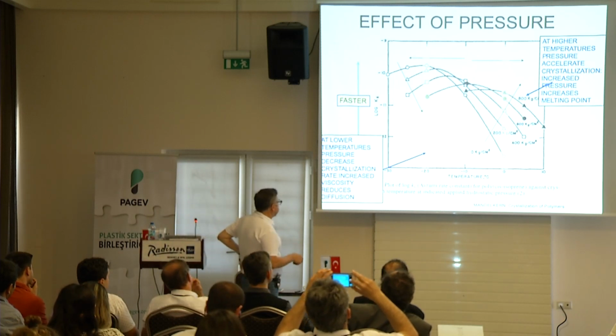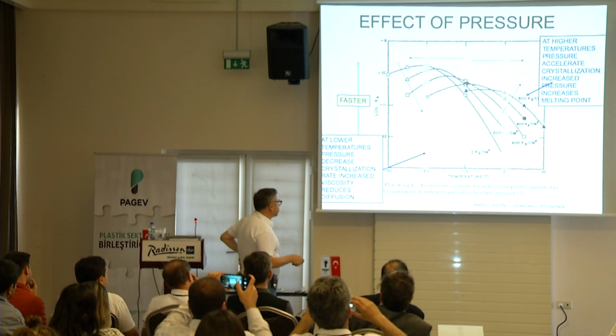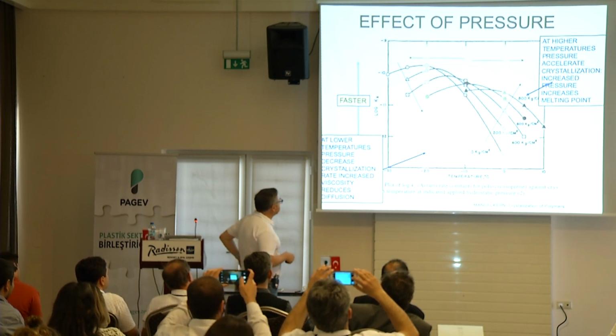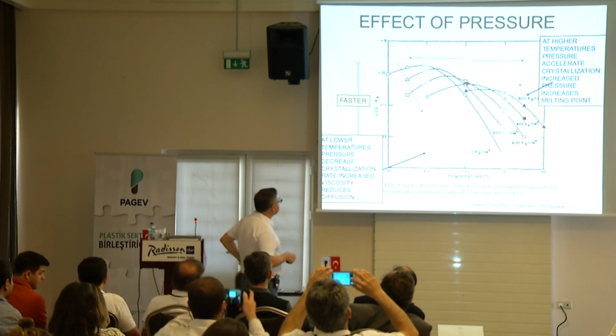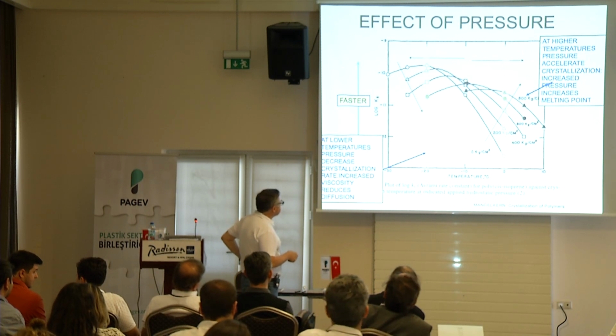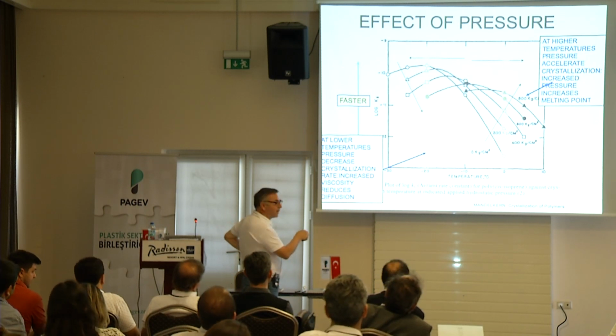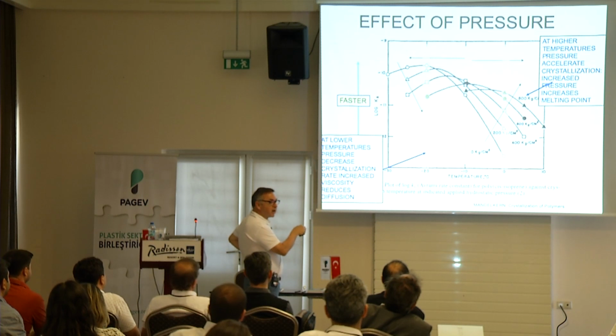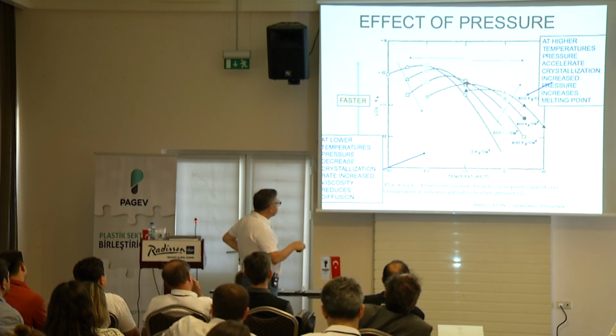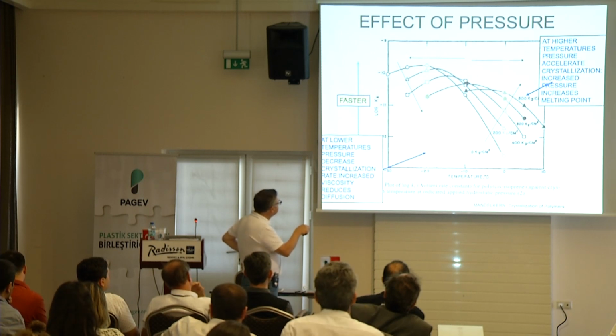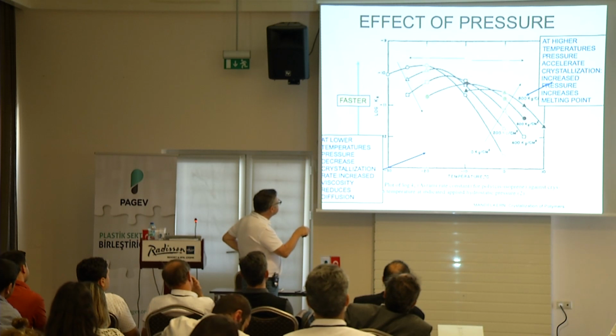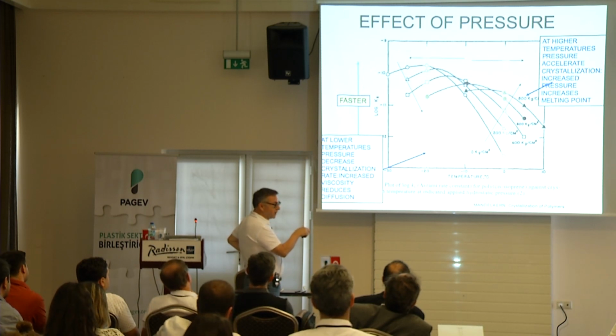So this happens to be cis-polyisoprene. This is one of those lower melting materials. It's a crystallizable rubber. What's interesting here is this. Remember the Avrami kinetics? This is the Avrami constant. So if you are at low temperatures, look what happens. The higher the pressure, the lower the crystallization kinetics. At higher temperatures, opposite.